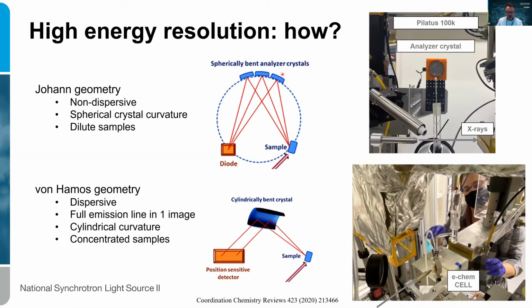It's done either with spherically bent analyzer crystals that refocus the fan of emission onto the detector, non-dispersive or dispersive with some modifications, and they work very well for dilute samples. The von Hamos geometry, which requires a cylindrically bent crystal, is a dispersive way of doing the emission spectroscopy with position-sensitive detectors. They usually require more concentrated samples.